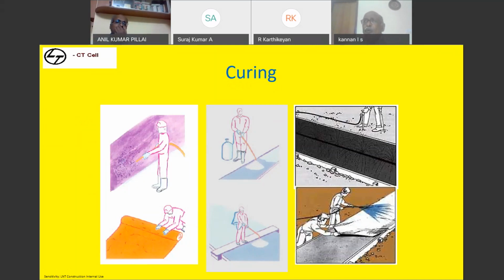Depending upon your secondary finish, suppose you have any subsequent finishes like your painting or tiling, or your wall finishing, go with only acrylic based. Don't go with wax based, because once wax based is done you will not be able to remove the wax based curing compound from the surface. Nothing will adhere. It's very, very difficult. Probably you have to grind and remove the surface. So instead of that, go for an acrylic based curing compound.